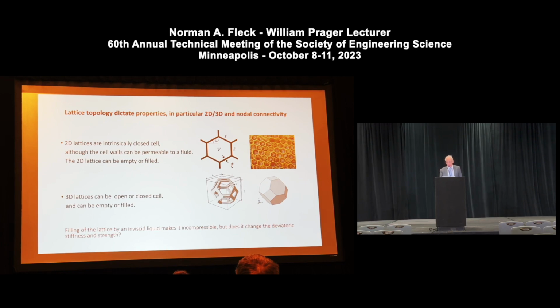For the hexagonal honeycomb, it's 3, and so one expects the in-plane response of the honeycomb to be weak and compliant. Whereas if it was much higher, such as a fully triangulated lattice, nodal connectivity of 6, then the structure would be a stretching structure, much stiffer. In 3 dimensions, the nodal connectivity of this Kelvin foam, for example, is much less. It's only 3 to 4 typically, and it's less than the transition value of 12, and so an open cell structure like this will be compliant and weak.